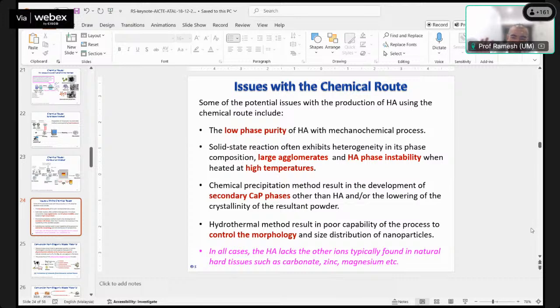Remember, just now there are two routes that we can produce HA. One is chemical route. There are some issues with this route. Some of the issues is the purity of the HA itself through the mechanical chemical process. Normally the powder produced from these techniques, even for the chemical precipitation, are not highly crystallized. So subsequently you need heat treatment to obtain a highly crystalline material. You also have problems with agglomerates with this chemical route. As I mentioned, that's always the challenge.